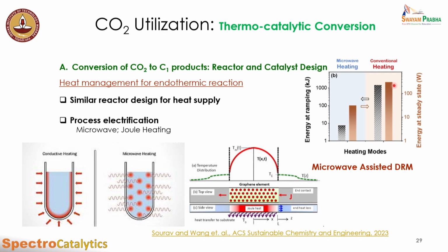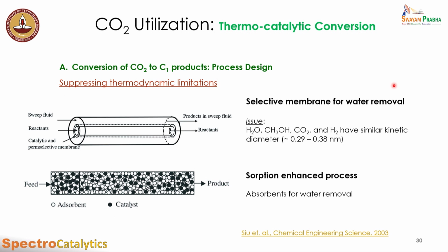With these things, we also have thermodynamic limitations, because from the reactant we are forming the product. If we can effectively take out the product, we can push the reaction forward. One approach is a selective membrane which can remove the water that is formed, though the issue is that water, methanol, CO2, and H2 all have the same kinetic diameter. The other is using an adsorbent with the catalyst which can absorb water, and since one product is taken out while the reaction is happening, the reaction can move in the forward direction.